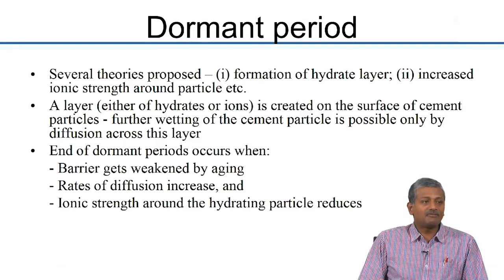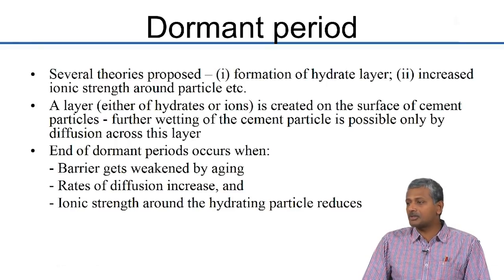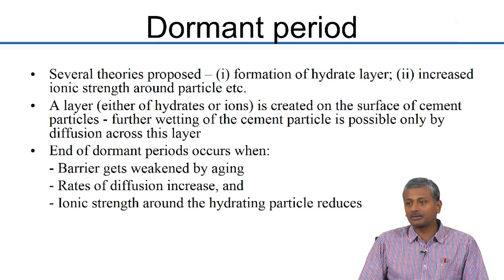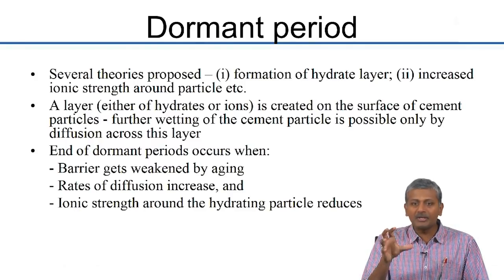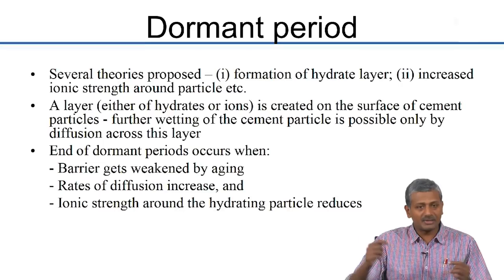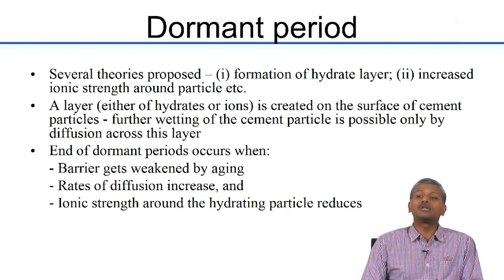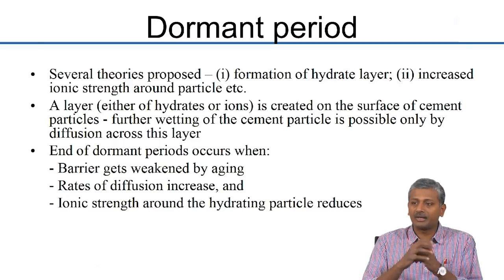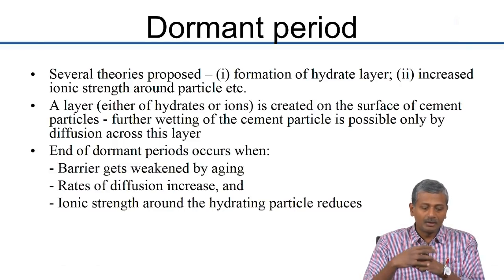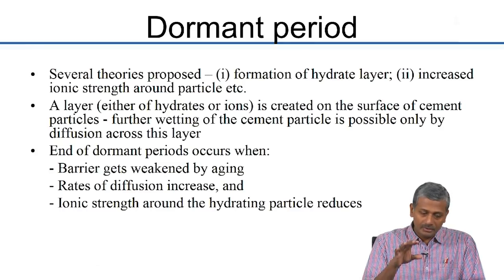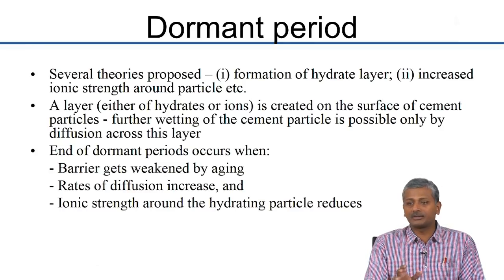The dormant period was discussed briefly: apart from the barrier of hydration products theory, there can be other explanations — one is increased ionic strength around the particle. When cement is placed in water, immediate dissolution from the surface increases ionic concentration around the particle, making it difficult for water to penetrate and react with the remaining unhydrated cement. This ionic strength also acts as a barrier.